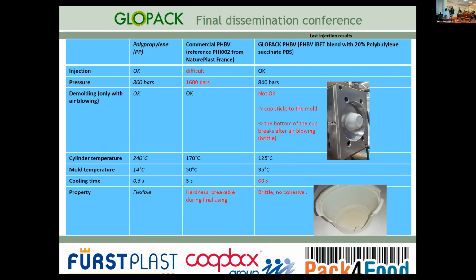So here, this is the result for the PHBV compound. Injection was okay because one of the parameters they worked on was to have a melt flow index as close to polypropylene. So this is a good point. But for demolding, it was not okay because the cup sticks to the mold because of some component or global properties. And the bottom of the cup breaks during air blowing.